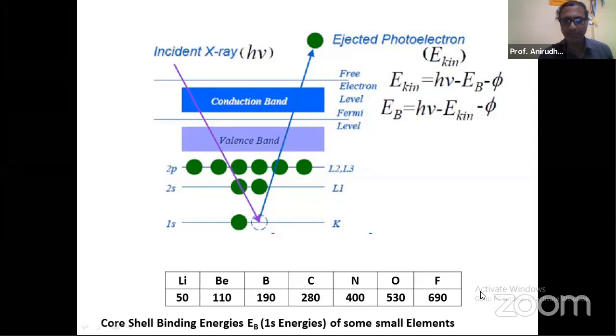So therefore, if you are suspecting nitrogen in your compound, when you subject it to X-ray photoelectron spectroscopy, and if you are sure that your X-ray is powerful enough to extract an electron from the 1s orbital, and you are getting a binding energy, because you are suspecting nitrogen, that is also important. You are trying to confirm whether it is nitrogen or not. Then if you are getting a binding energy which is either 400, which confirms elemental nitrogen, or a value close to it, say for example 401.7, or let's say 398.2, then you can be fairly sure that there is nitrogen in your system, and that it is bonded. The reason to infer that it is bonded is that the binding energy value you are getting is not exactly equal to 400, but is in a band plus or minus some value around 400, which denotes bonding. We will see why it denotes bonding.